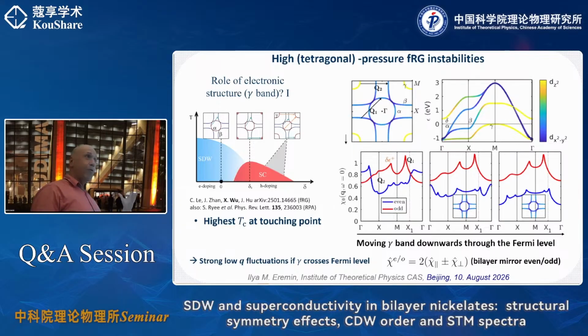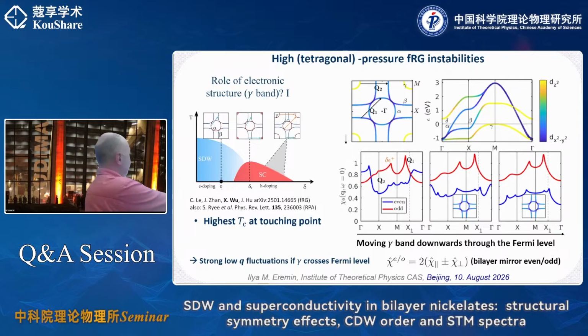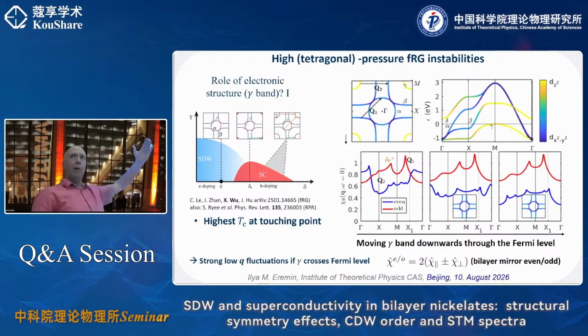I am ready to accept a theory which says, look, z squared is completely localized. Well, one can take this. If you want, you can work with this. I mean, it would not agree with ARPES data on thin films, where we see that the gamma pocket does cross the Fermi level. Plus, there is another problem, which is that along this direction, along gamma-M, z squared antibonding and antibonding x squared minus y squared are completely degenerate by symmetry.